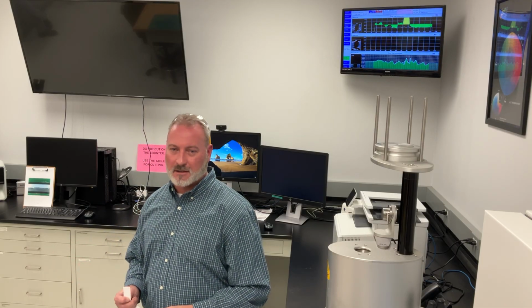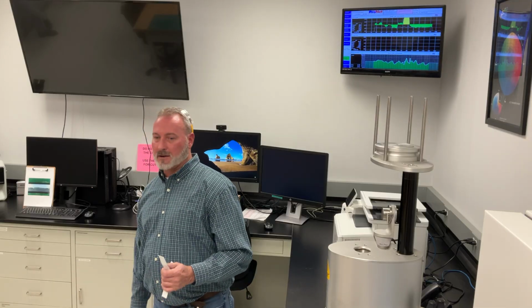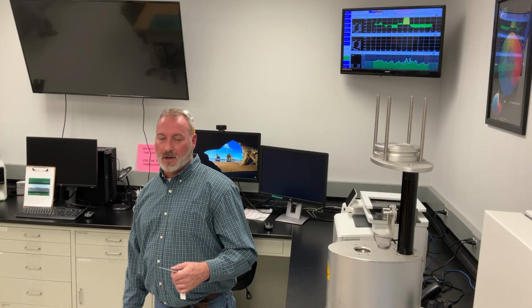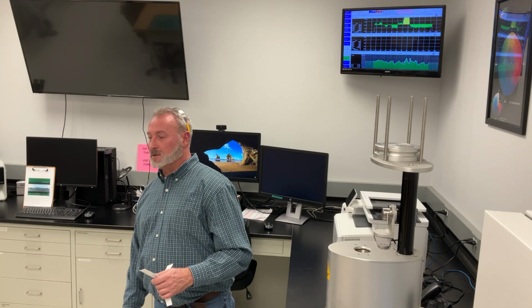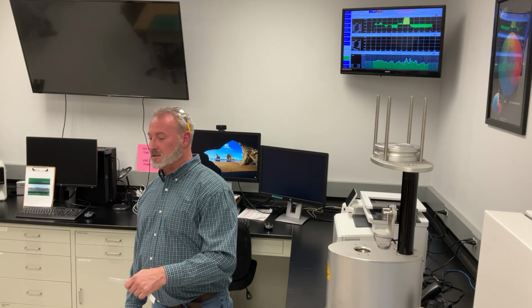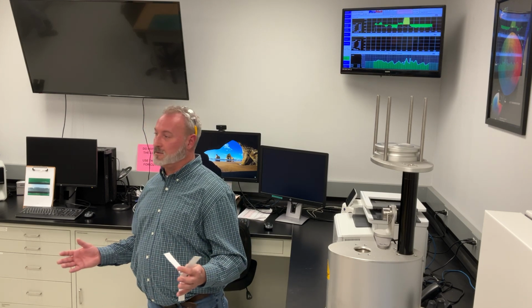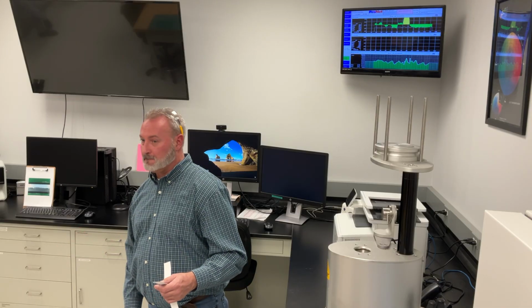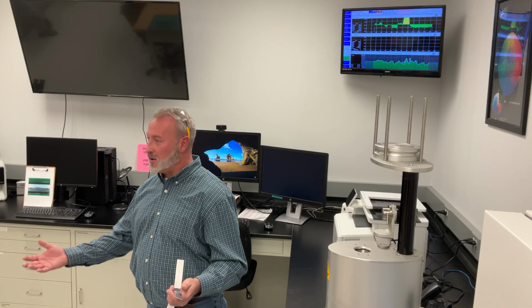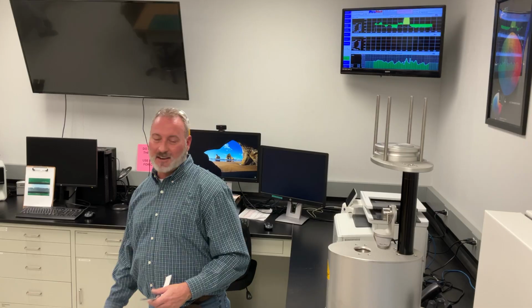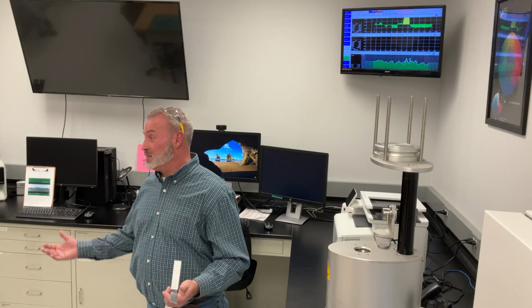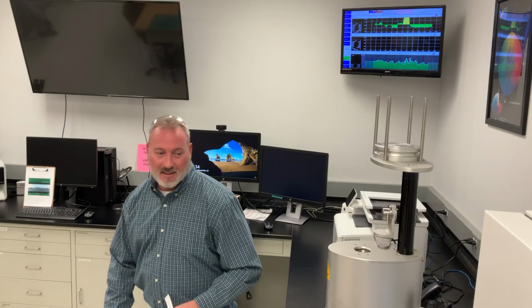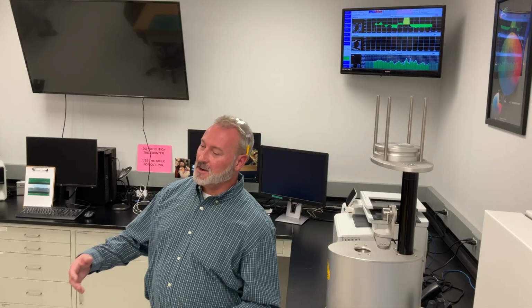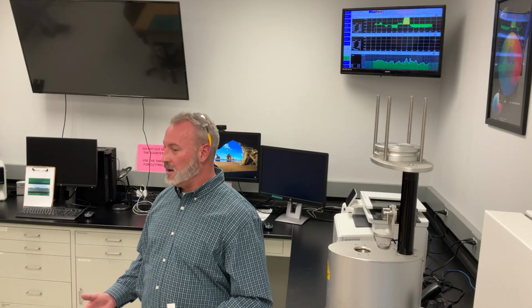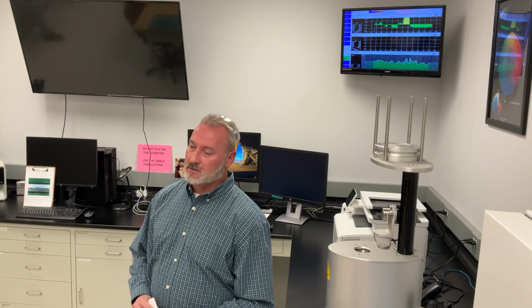380, 400, something like that. So, well above spec on it. We also have an ozone chamber, right? Same deal. We put samples in this ozone chamber and we expose it to ozone, whatever that is. As a kid, we always heard about the hole in the ozone layer. I never knew what ozone was, but I got a chamber that apparently creates ozone. We put it in there for 7 days, we pull it out, we bend it again, and it cannot crack. We don't ever have a failure on that one either.